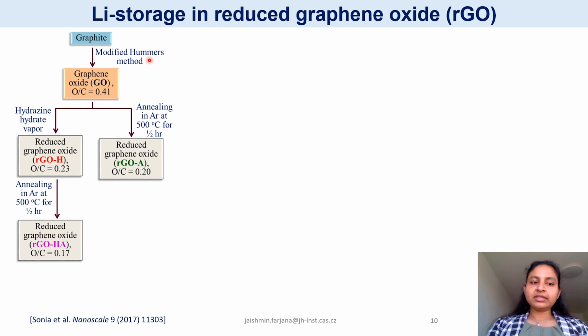Now, if we consider commercialization of graphene based lithium ion batteries, then reduced graphene oxide is a better candidate because they are cost effective and there is a possibility of mass production of this reduced graphene oxide. But these RGOs have more defects and more oxygen functional groups in general, that I was mentioning in a few slides back.